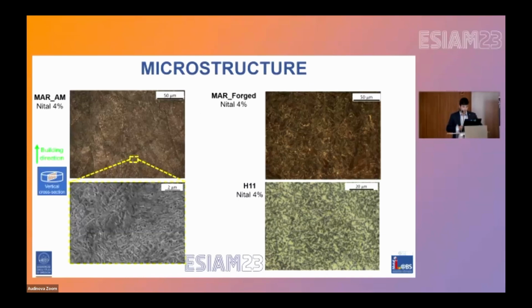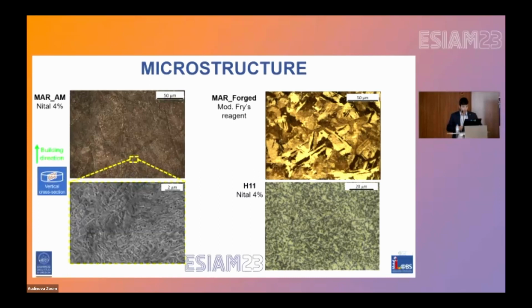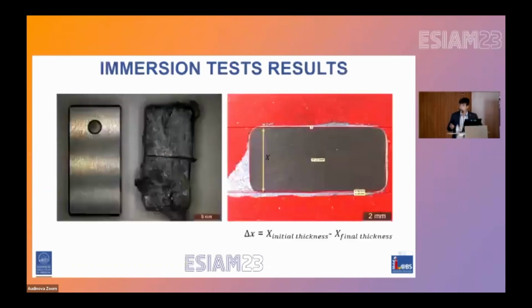On the other hand, the microstructure of forged samples reveals packets or blocks of lath-type martensite with very fine boundaries, following a Nital etching, while after Fry's reagent etching, the different orientation of the martensite blocks can be instantly recognized. And finally, for completeness, the microstructure of the H11 sample is also presented here.